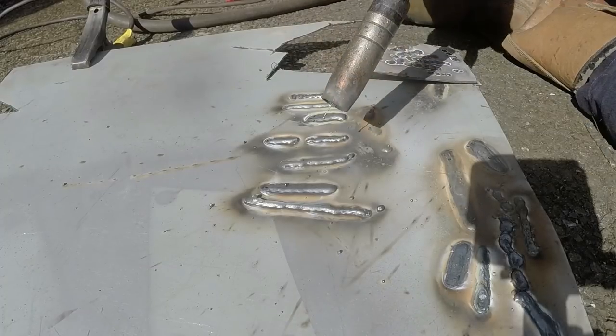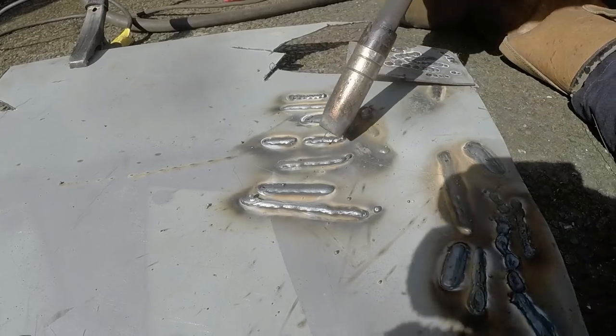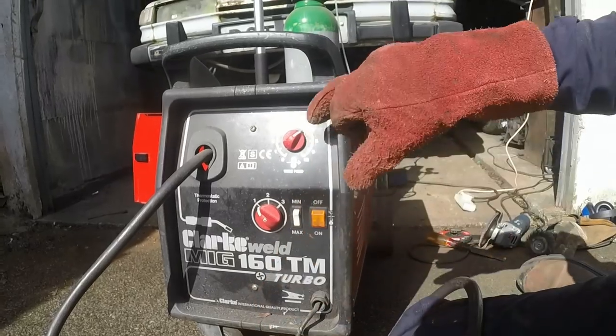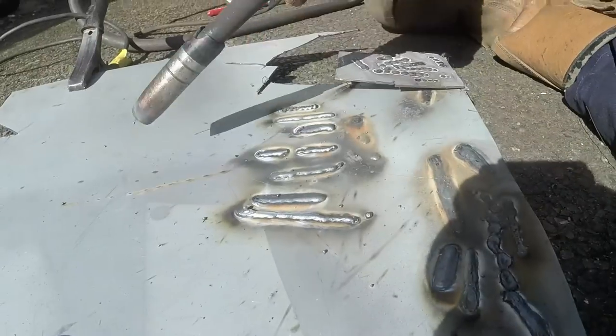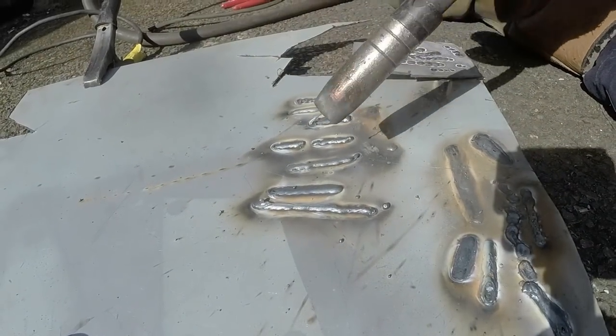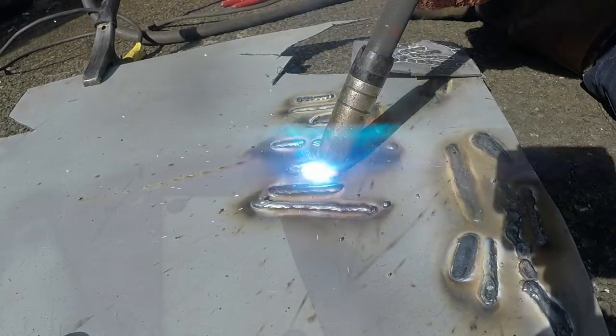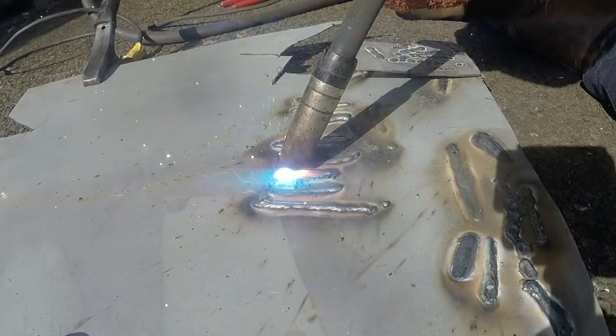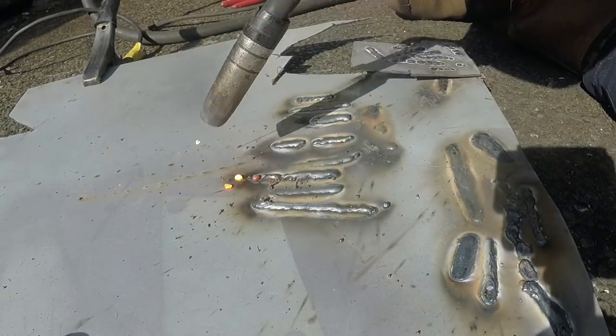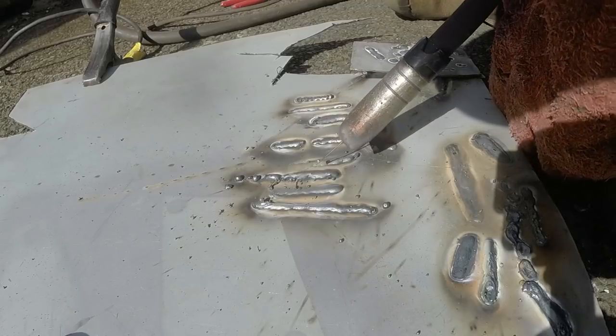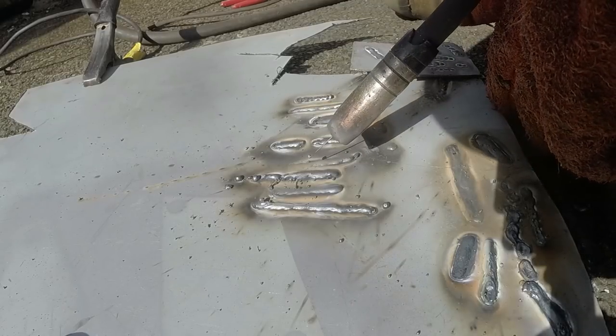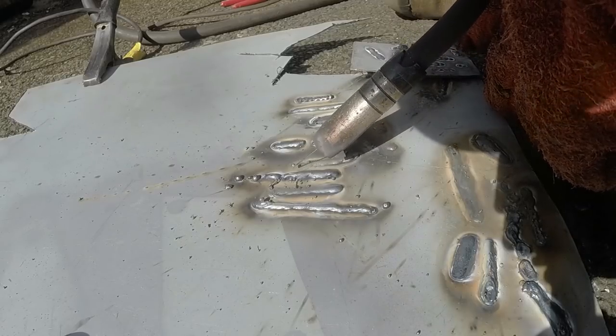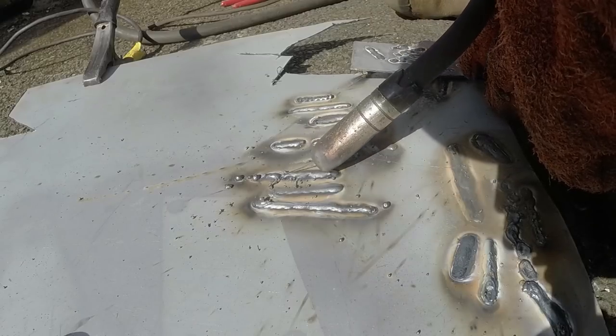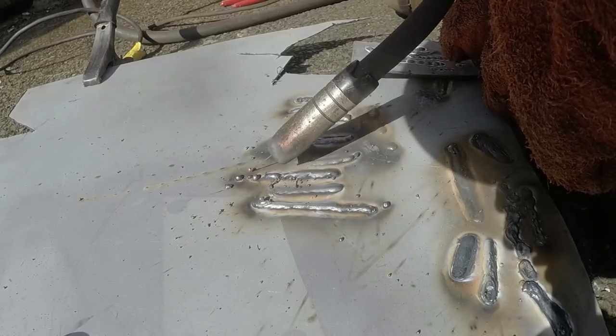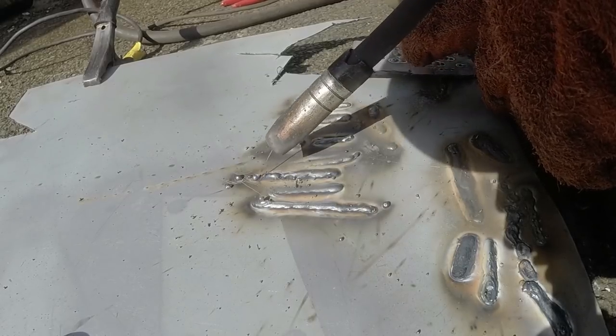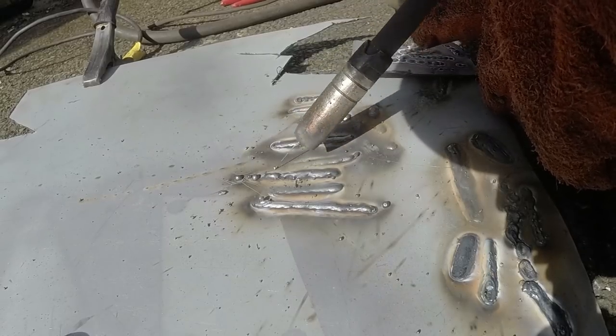So I'll try and do this one-handed again. Oh, and just for reference, if anyone has this welder or is thinking of getting it, we're on one max, just a gnat's cock over six. So you can see we've had the opposite problem. We've been delivering so much wire that the power coming from the arc isn't sufficient to cause it to melt and fuse and burn in fast enough. So the wire is actually deflecting off the surface and we're getting a really inconsistent, spattery weld. In fact, it's not welding at all. Can you see how these blobs are barely on there? They're just sitting on the surface, which is not what you want.